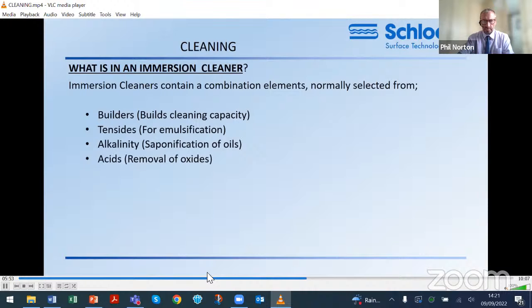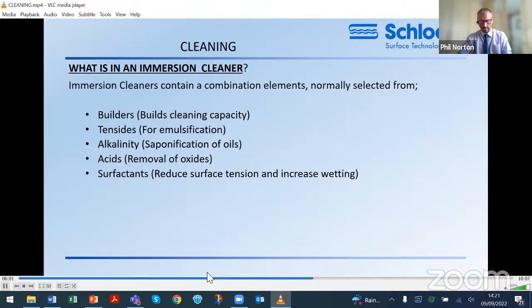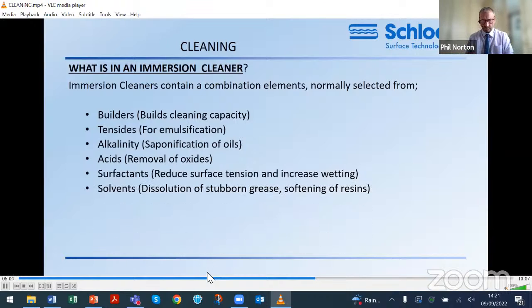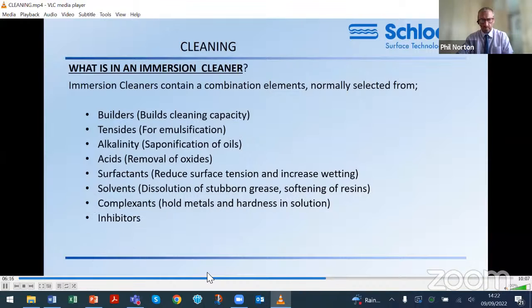Acids for the removal of metal oxides. Surfactants, which reduce surface tension so that the other ingredients in the cleaner can get to the surface and do the job. Solvents, sometimes used to remove oils and grease. Complexants, these hold contaminants in the solution so that they don't interfere with the cleaning process. And inhibitors, these are used to prevent strong chemicals and acids from attacking the substrate.